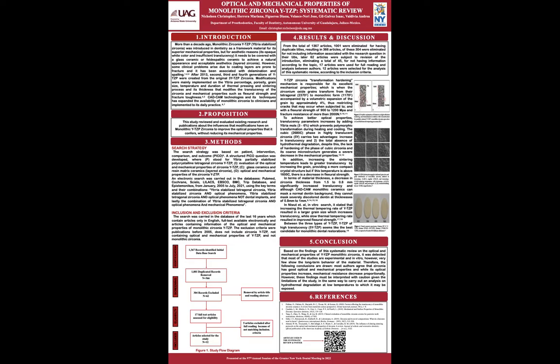But due to the opaqueness and insufficient translucency to use it as a monolithic restoration, we have always opted to add layers of ceramics to the zirconia. But it has been shown that layered zirconia is more prone to fracture and delamination. The reasons are differences in the coefficient of thermal expansion, the contraction of the porcelain during the firing process, and the overload and fatigue between the interfaces of those layers of ceramics.